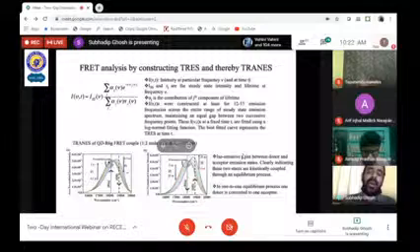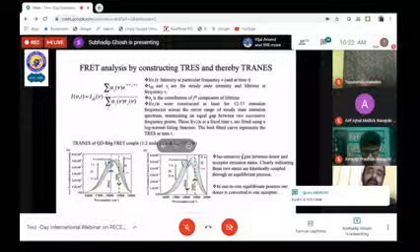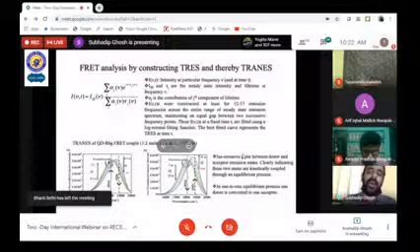So when the donor peak and the acceptor emission interfere, what we did was split the individual spectra using a biexponential curve, fixing the peak positions corresponding to rhodamine 6G and the quantum dot.